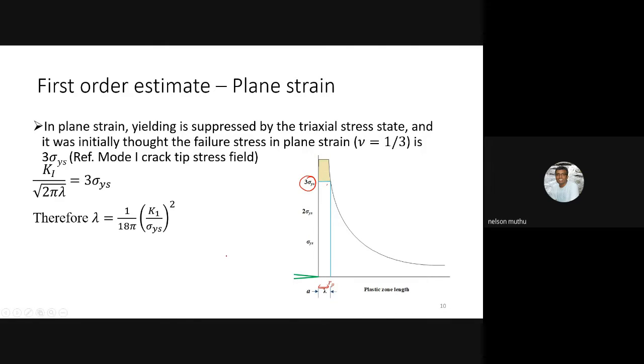So what you can see here is that when k1 by square root 2 pi lambda is equal to 3 sigma ys, you will get the value of lambda as 1 by 18 pi times k1 by sigma ys whole square. Whereas in the case of plane stress, lambda was how much? 1 by 2 pi, k1 by sigma ys whole square. That means your plastic zone size in the case of plane stress is much higher, almost 9 times higher than what you see in the plane strain case. So what is its implication?